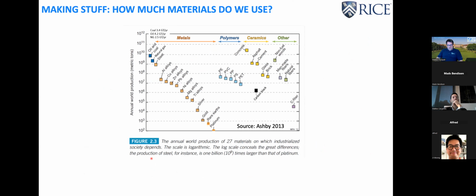What are the opportunities? So this is a plot from a book by Ashby from Cambridge on how we use materials, and we put oil and gas here for reference. And we see there's a few areas, but one commonality is structural integrity is key for widespread use. So carbon black, for example, is about as cheap as steel, about $1 a kilogram, but is used in a very small quantity. Also look at the difference between polyethylene, polypropylene, PVC, which are all materials in the low $1.50 a kilo, and they're used at a scale that's almost 10 times or larger than carbon black.